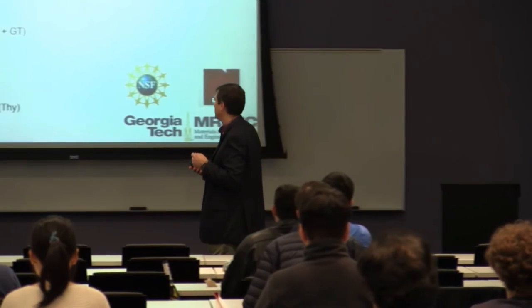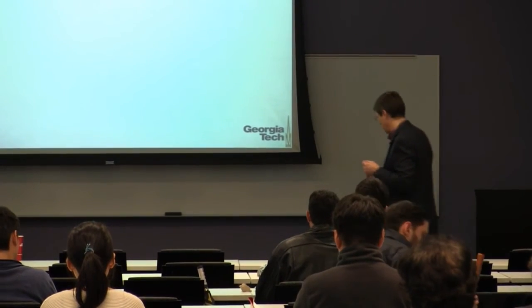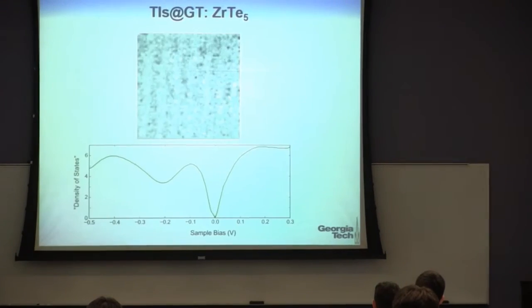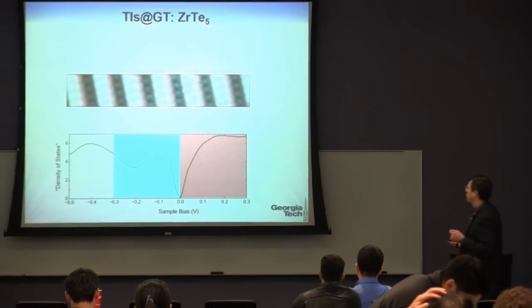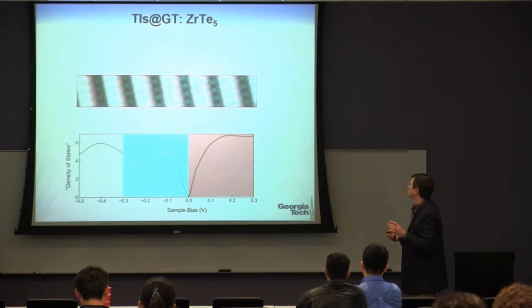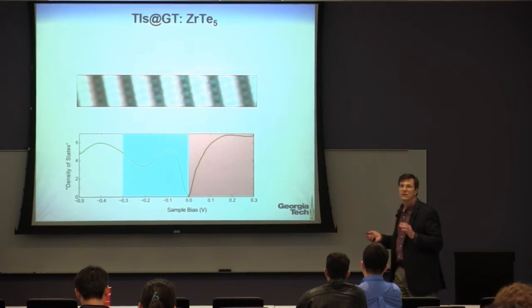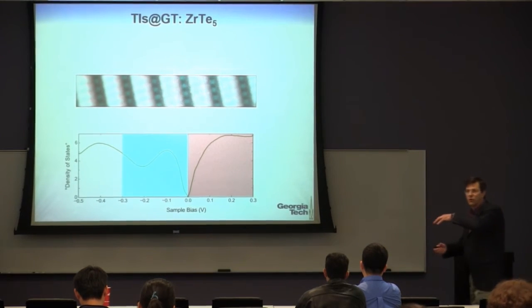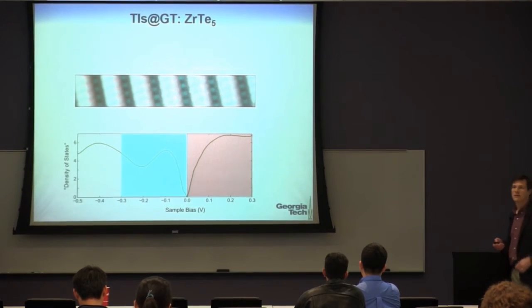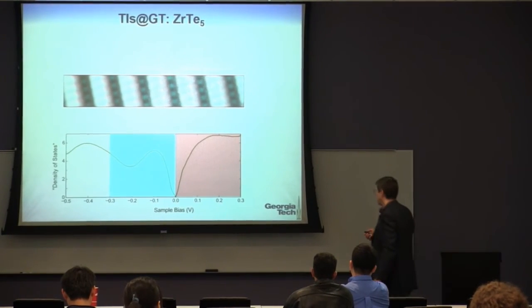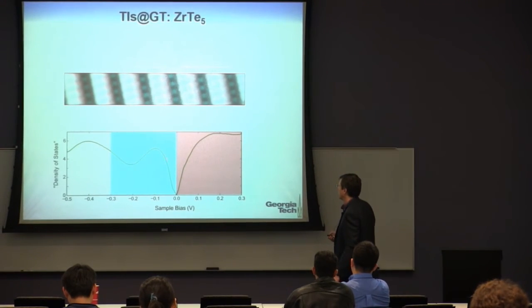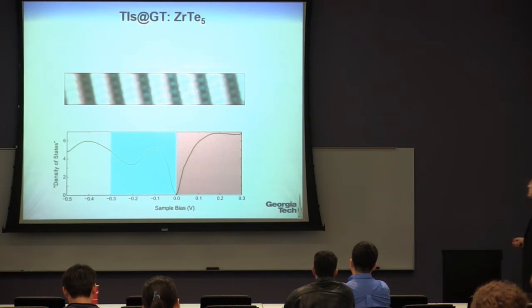The strips that I showed were part of the crystal structure. I didn't show you the crystal structure. The strips that you saw in the movie were these strips. They're dimers. They're tellurium dimers. Okay. They live on top of the zirconium in this case, covering it all up, in fact. Yeah, the surface states would live in here. In fact, we think that this may be a surface state. We are in the midst of comparing some of these things to infrared results that Zhigang Zhang has done, as well as some band structure calculations to figure it out for sure.